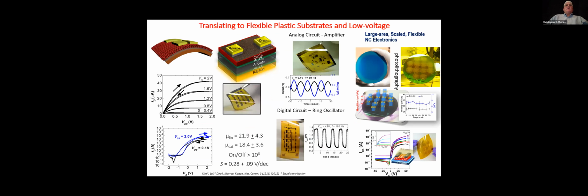But when that exchange is done thoughtfully, and I will apologize, I'll just go to the next slide for time, we can begin to build, and this in particular is led by Sherry Kagan and her team, from the nanocrystal based films, these artificial atoms assembled together, we can start building out analogs of all of the key components in microelectronics to make different types of solution processable devices that have performance that greatly exceeds the best of breed organic semiconductors and starts to eat into the low end of a number of classic inorganic polycrystalline semiconductors in terms of their performance characteristics.